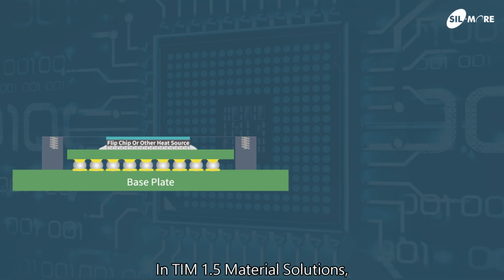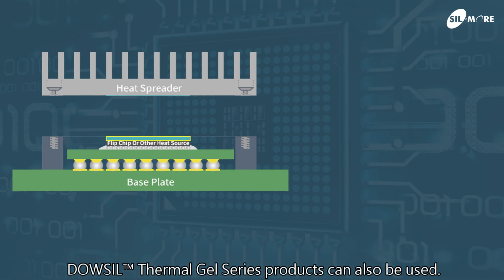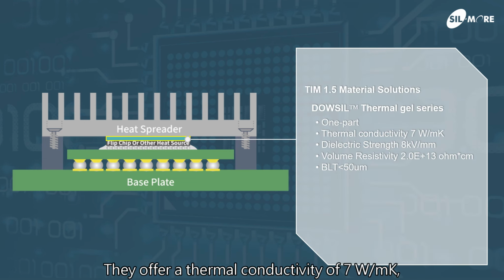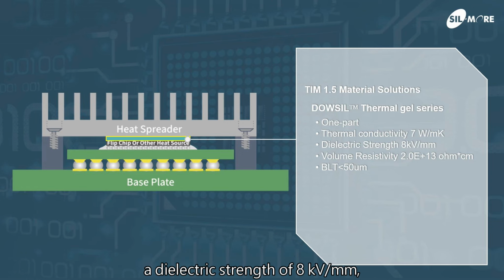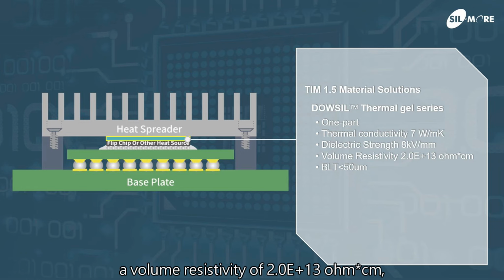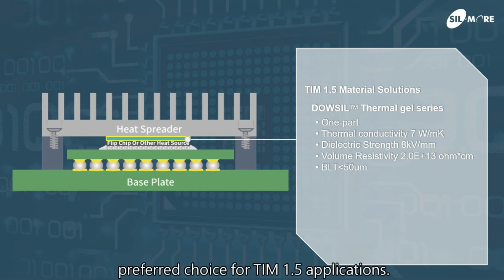In TIM 1.5 material solutions, DOWSIL™ Thermal Gel Series products can also be used. They offer a thermal conductivity of 7 W/mK, a dielectric strength of 8 kV/mm, a volume resistivity of 2.0 times 10 to the power of 13 ohm·cm, and a bondline thickness, BLT, of approximately less than 50 μm. These characteristics make them the preferred choice for TIM 1.5 applications.